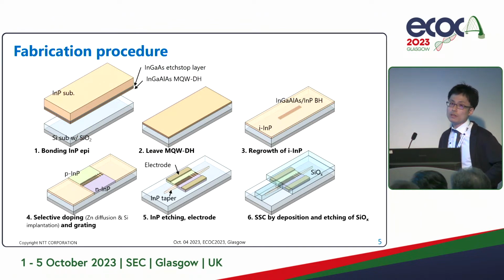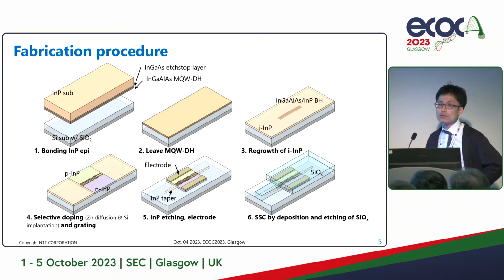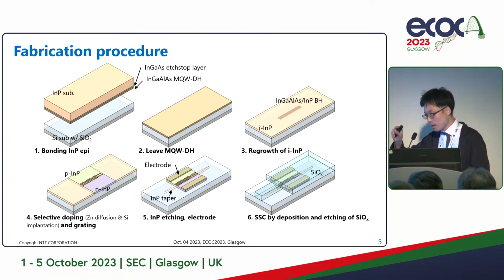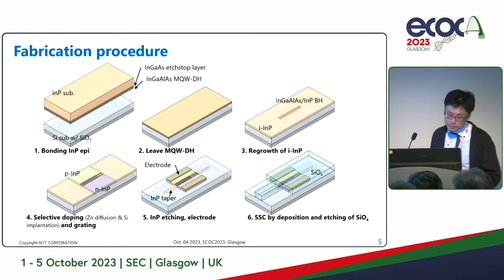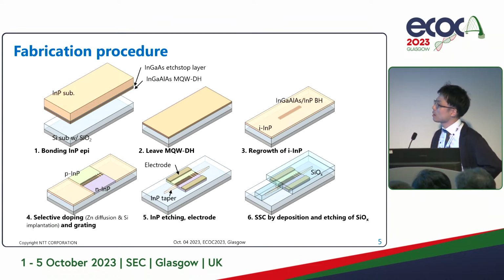And this is the general fabrication procedure. The fabrication begins with epitaxial growth on an indium phosphide substrate. We grow an indium gallium arsenide etch stop layer and MQW layer and bond this epitaxial wafer to the silicon wafer with an intermediate silicon dioxide layer. And then we remove the indium phosphide substrate to obtain this very thin III-V layer on silicon structure. And we define a mesa stripe and bury the mesa to fabricate a buried heterostructure by carrying out the regrowth of indium phosphide on the indium phosphide thin film bonded on the silicon. And then we form the P and N-type doping layers by zinc thermal diffusion and silicon ion implantation. After that, we form the indium phosphide mesa, a tapered mesa, and we form the spot size converter by depositing the silica-based materials.